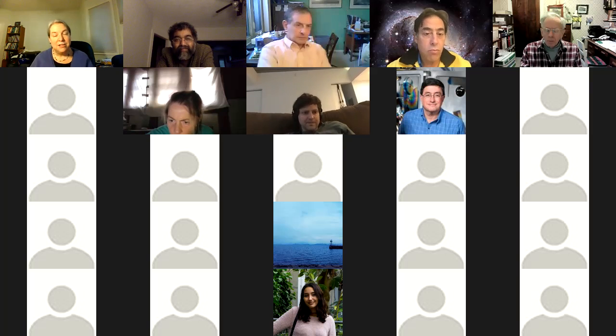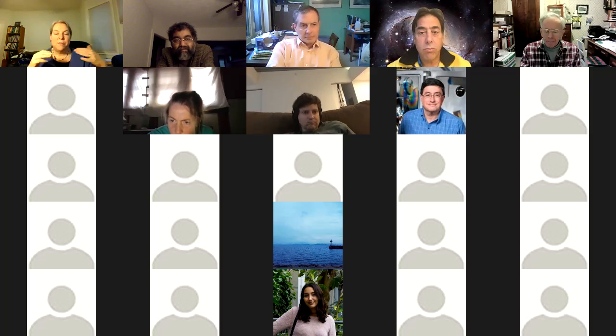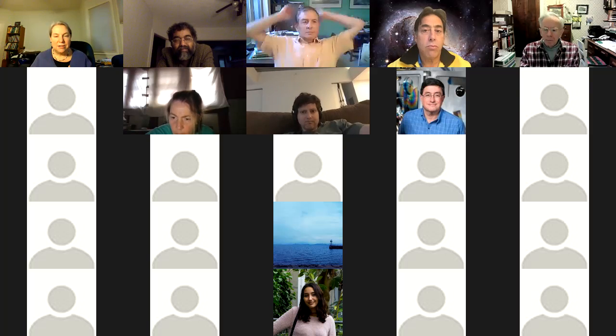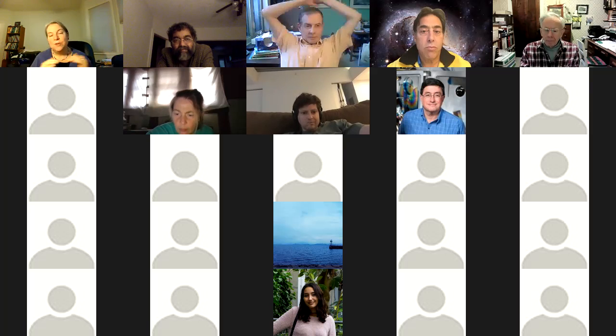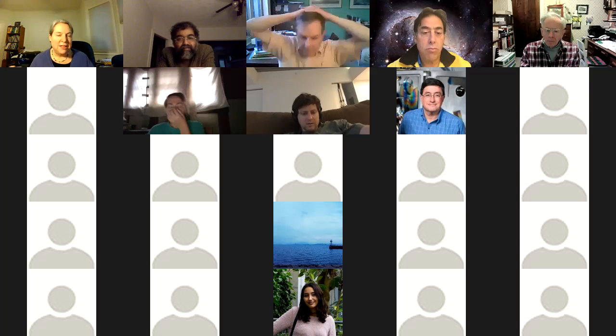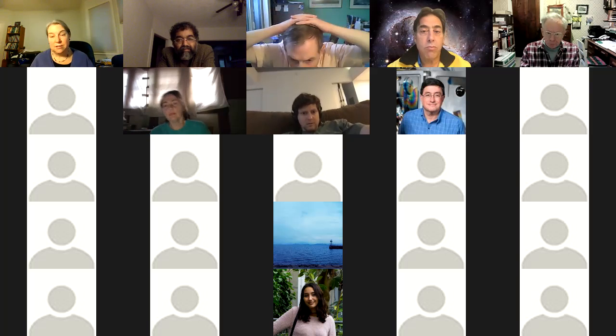We can't do that. On the other hand, Jonathan used linear elasticity to model the deformation of a very thin elastic film on a rigid, not moving substrate. And the displacements are tiny and the linear approximation is fine. But he wasn't able to do that for the whole sample with the edge effects. He was essentially doing a very simple, more or less two-dimensional case that he could solve analytically. And the finite element lets us do the full 3D problem.